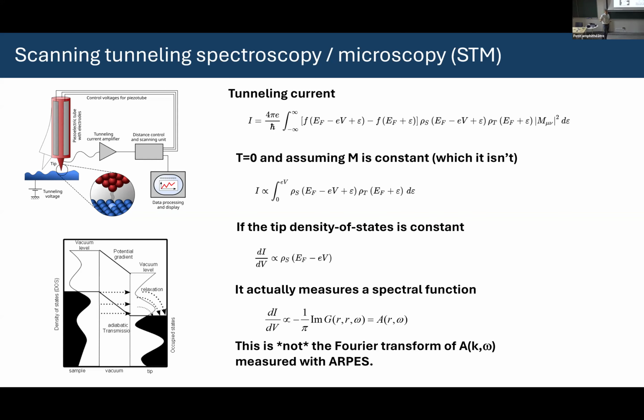Those will scatter, and I'll see interference patterns around them in an STM. Those are called Friedel oscillations. They're screening of the electron gas, and they have wiggles. The period of those wiggles is kF, or 2kF. And if you take those wiggles and Fourier transform, you can actually see the Fermi surface of gold. This was done by Ward Plummer in the early 90s.